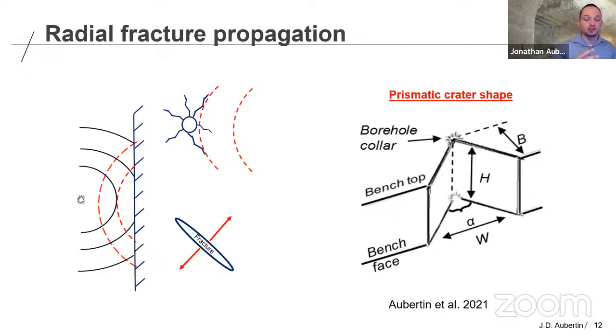This P wave, this compressive wave emanating from the blast zone, travels radially away from the blast zone and is reflected in tension by any given free surface. Typically in blasting, you have this big bench face in a mine, or underground it would be cut in the middle of the face. You have this free surface that reflects the wave in tension. This wave in tension comes back towards the blast hole and interacts with the radial fractures I talked about previously. The tensile wave basically opens up and props up those fractures, which allows those fractures to reach all the way to the free face.